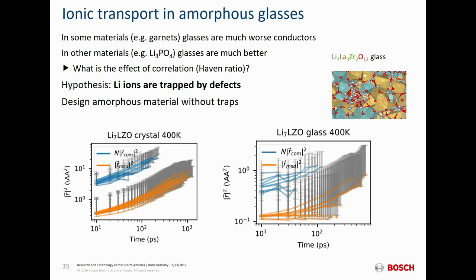More broadly, disorder in general — in this case frustration as sublattice disorder — seems to be an interesting tool for engineering ionic conductivity in these materials. By far more materials, when made amorphous, start conducting ions better. We don't fully understand why — there are some hypotheses based on percolation models — and some materials do better while some do worse. But the fact that most materials do better when amorphized indicates that disorder and frustration are actually interesting design tools for superionic conductivity in general.